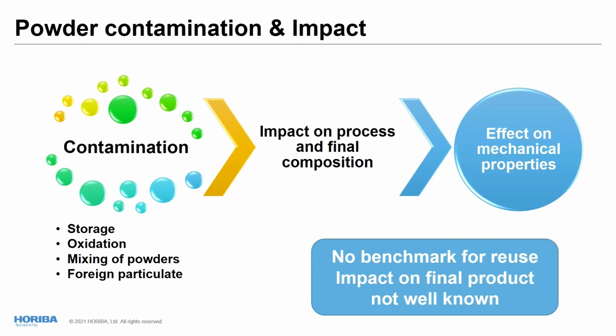The contamination can happen at multiple levels in the process. It can happen at the manufacturing and the storage of the fresh powder. This fresh powder can oxidize over time. There may be some accidental mix with other powders of different composition, or also the presence of foreign particulate. The recycling of the powders, as Anderson was showing, where we recycle a part of the powder, makes the process more exposed to contamination issues. And since there is no real benchmark for reuse, and the impact on the final product is not well known, it's really important to monitor the fresh powder, of course, but also the powder over the various cycles.